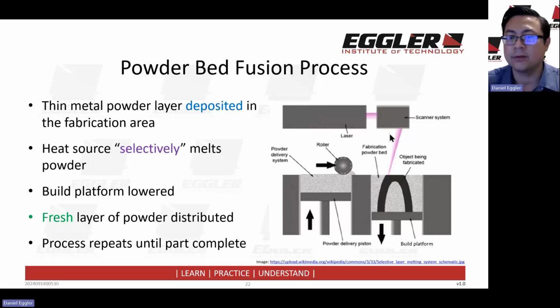Where it's different, particularly for powder bed fusion, is the control of what we call the melt pool. So as the laser is selectively melting the powder, it's controlling the size of that melt pool, it's controlling the temperature inside that melt pool, and as a result, it's able to control the phase of the material as it cools. Right, so this is a very key difference between welding and powder bed fusion, the ability to control the melt pool. And this is what allows it to be a very strong part, and you don't have those weaknesses that you would typically have with welding, right?